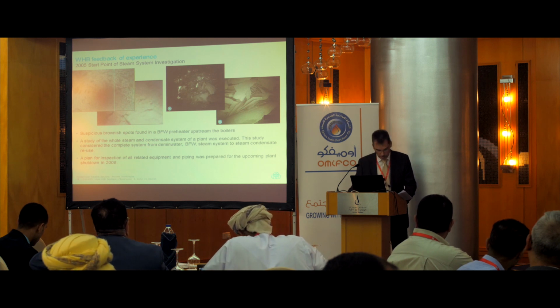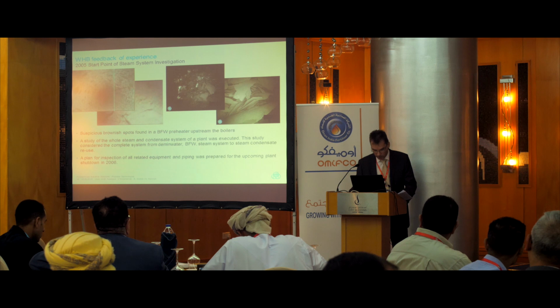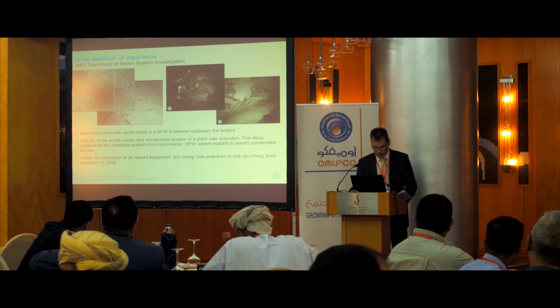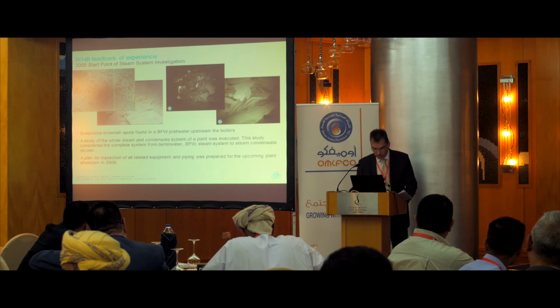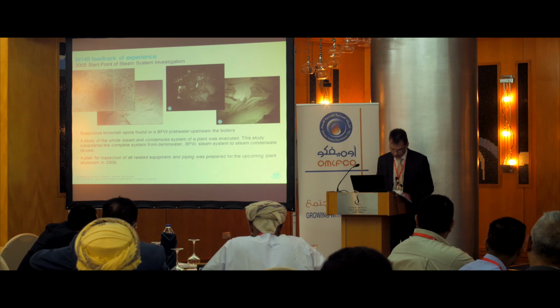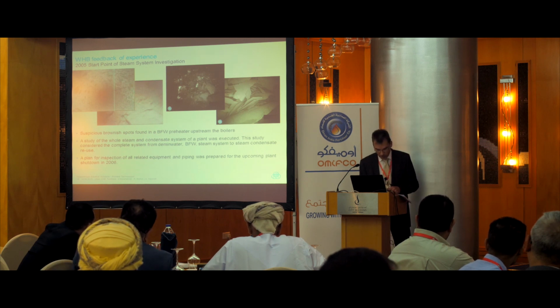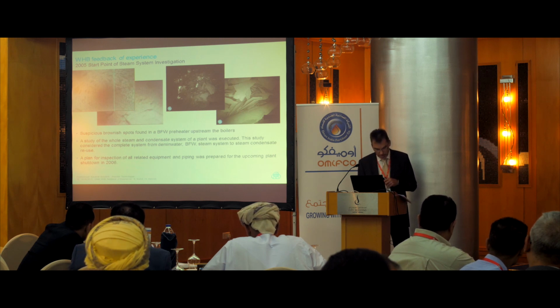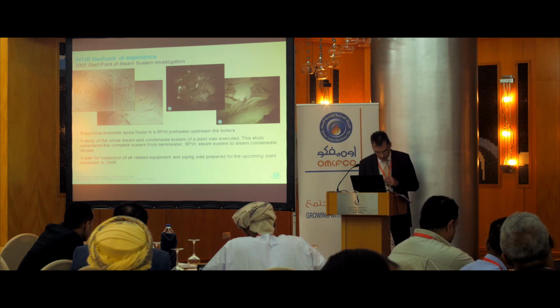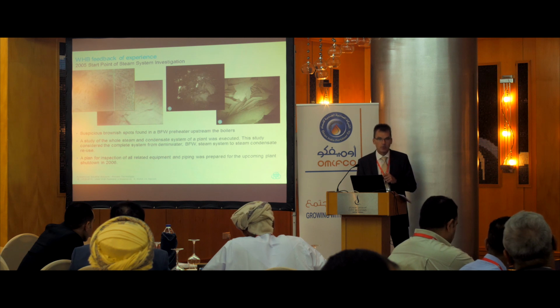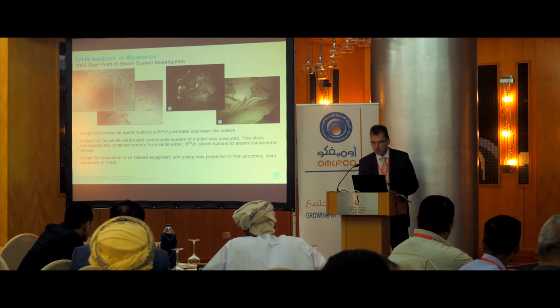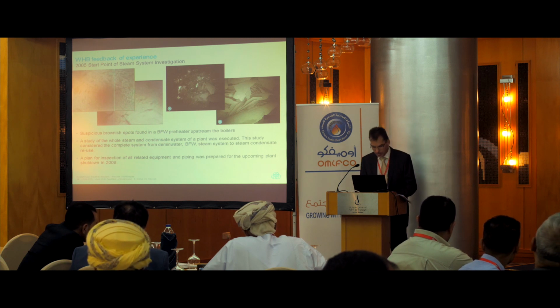Even if a dosing of oxygen scavenger is almost not required because of low remaining oxygen below 20 ppb, a certain amount of oxygen is always good for build-up of the passivation layer on the tubes, especially during commissioning. All these recommendations were taken over to all new fertilizer plants from 2005-2006 onwards. In addition, an automated blowdown operated by DCS, independent from plant personnel, was requested in all new plants. This helps to avoid that blowdown is opened or closed just by accident when the operator is outside, and not by a real automatic plan.